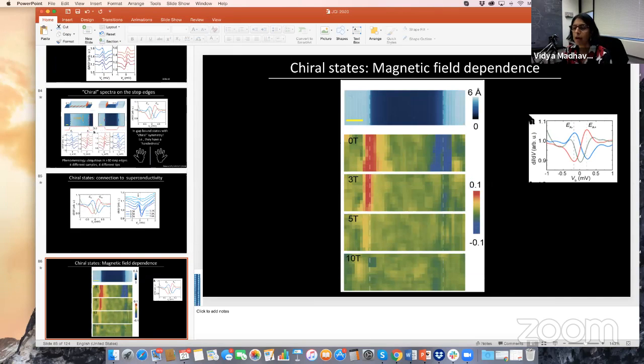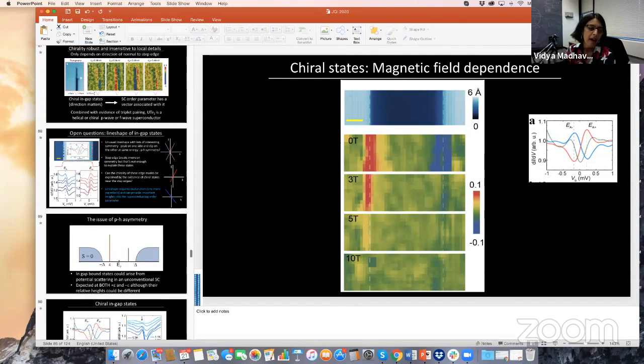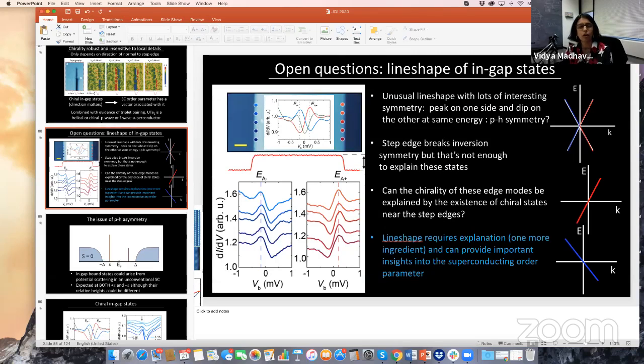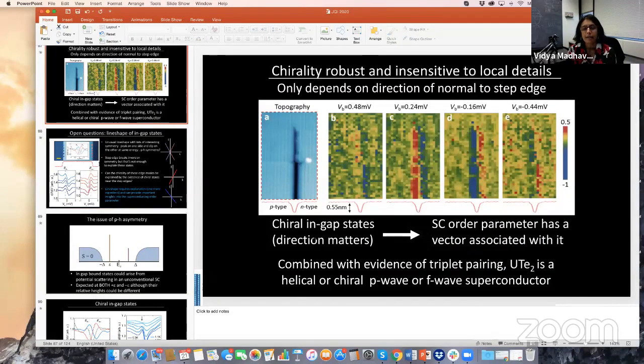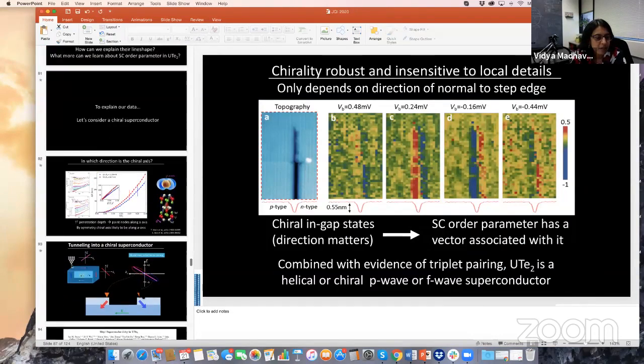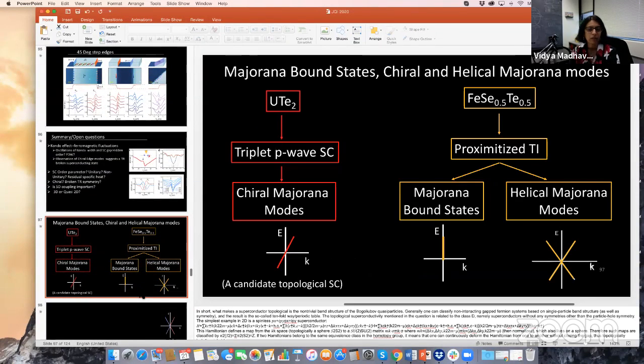And so we did a lot of experiments to show that these in-gap states were a consequence of superconductivity. And in fact, I'm not going to have time to go through all this. All I want to tell you is that the presence of these chiral states, which are actually sensitive to the direction in a superconductor, suggests that this might be a helical or a chiral P-wave or F-wave superconductor. And that's it. That's all I want to say. So let me just stop here. And thank you again for your attention.